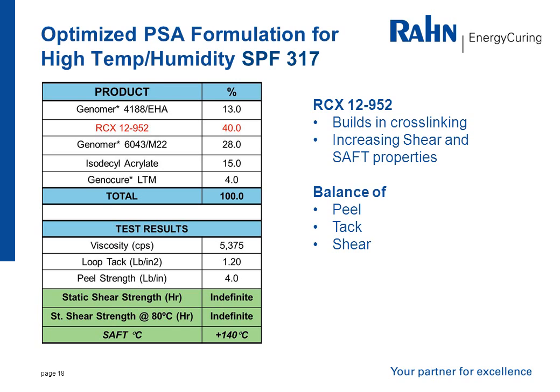By adding RCX-12-952, we build in cross-linking, therefore increasing shear and SAFT properties. In combination with our other elastomer component 4188, the tackifier 6043, and diluent isodecyl acrylate, the result is a good balance of peel, tack, and indefinite shear properties, as well as a notable increase in SAFT value. We move up to a failure of 140 degrees C.